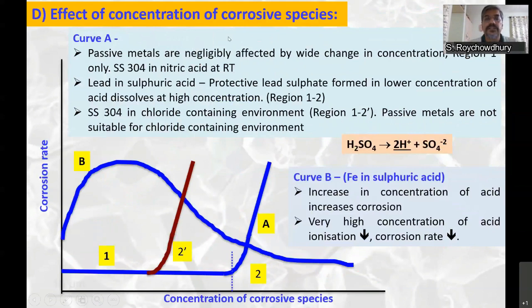Another is the effect of concentration of corrosive species. There are two types of behavior. We'll first see behavior A. Again, this is mainly for passive metals. Initially, to start with, we have a passive film, so corrosion rate will be very low, even though the concentration of corrosive species increases. And beyond a certain point, the transpassive region starts and there is a rapid increase in the corrosion rate. For example, 304 austenitic stainless steel in nitric acid. For very high concentration of nitric acid, the transpassive region is reached and it will start corroding at a high rate.